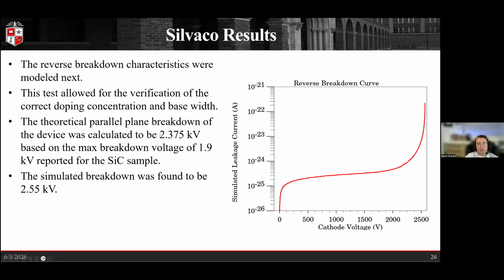So with this, that means our theoretical parallel plane breakdown would be about 2.375 kV. And in our simulation, you can see we're just past 2.5 at 2.55 kV. So relatively close match there, matching our physical device in theory.